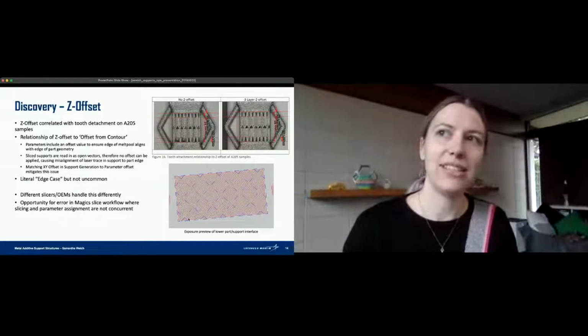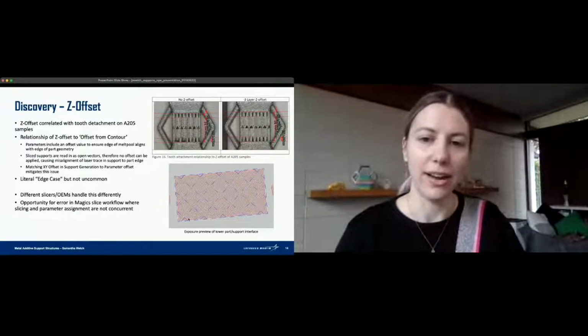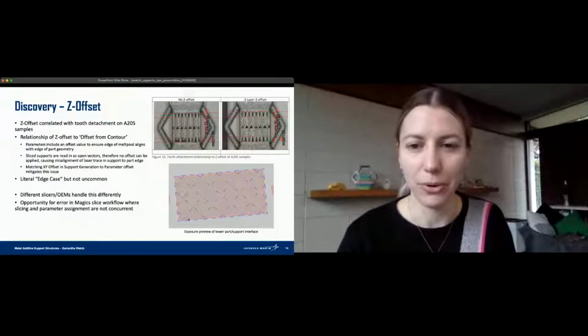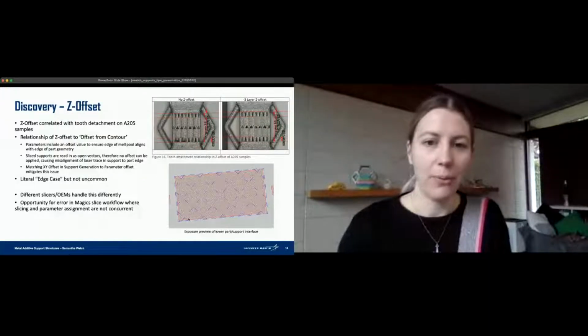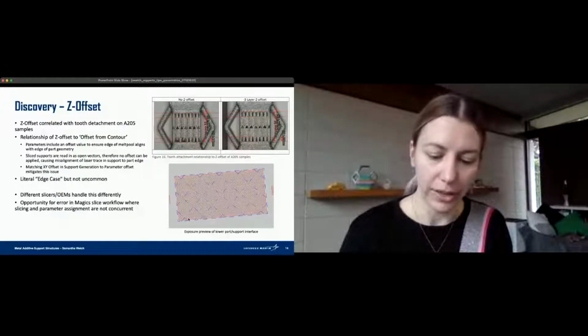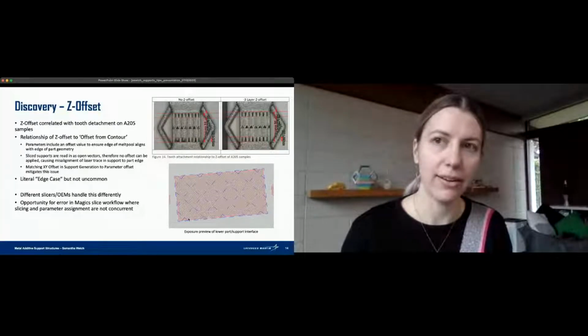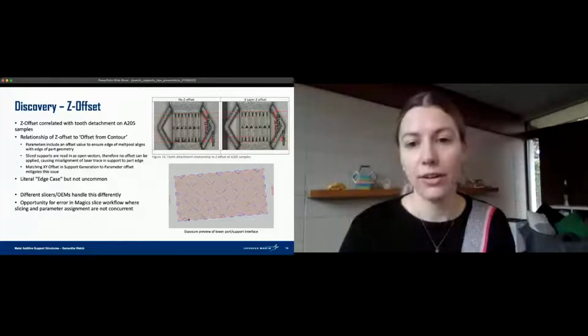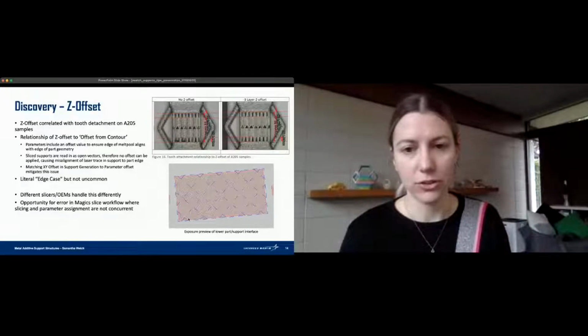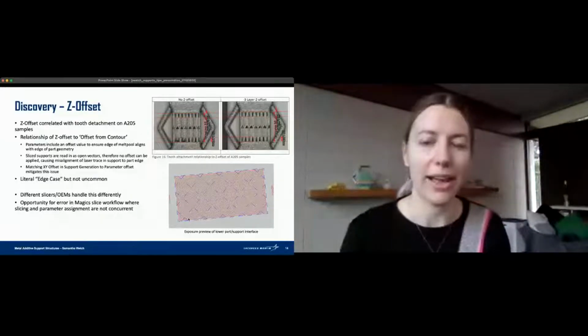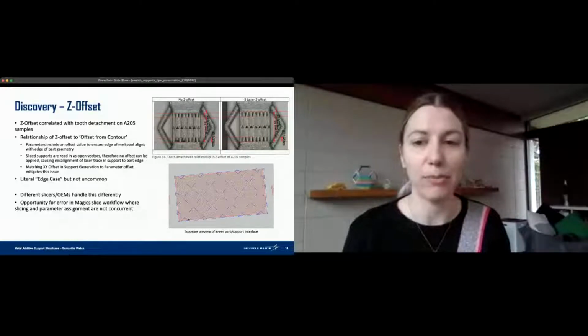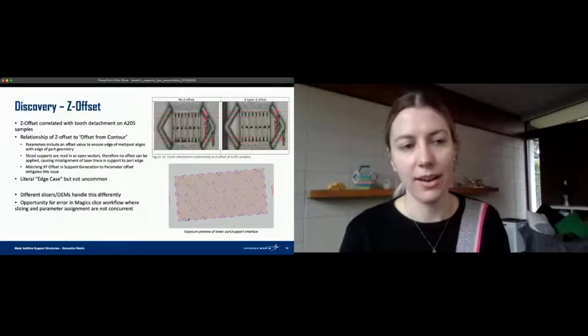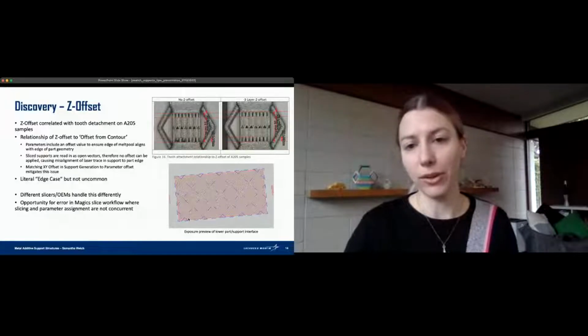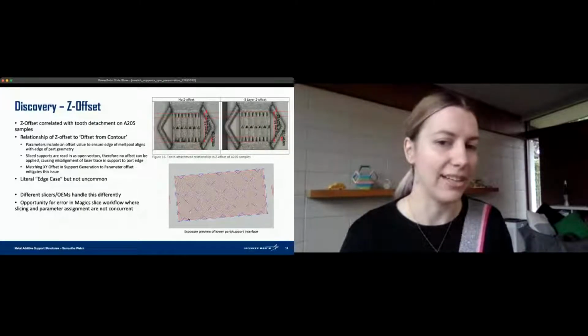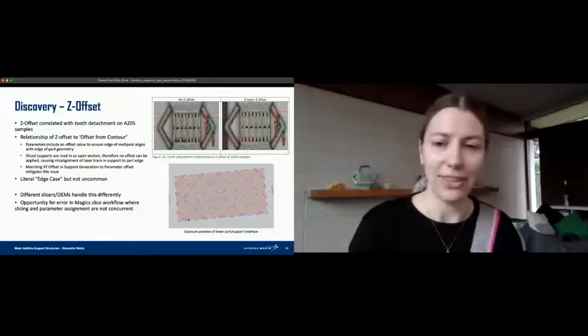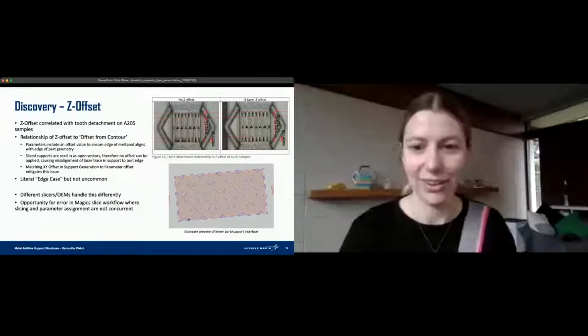It didn't quite make sense to me, given that I'm dumping a lot of energy in and then exposing a small support projection onto it. But when I looked closer, there are actually some relationships between a few other variables that were not being caught initially. So when we're doing these laser exposures, the laser's not actually tracing my part edge. It's tracing set inside of my part edge, because that melt pool offset needs to be set so the edge of my melt pool is going to be at my part edge so my part doesn't come out oversized. So when I slice my part, I've got these closed contours, that offset's applied, it's all good.